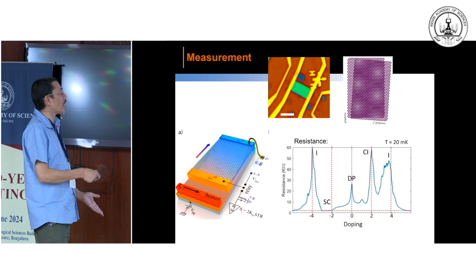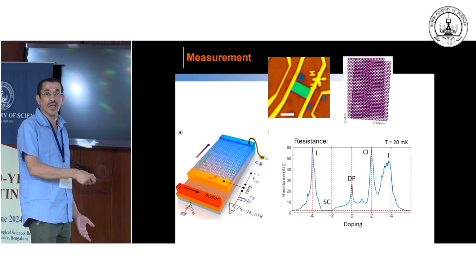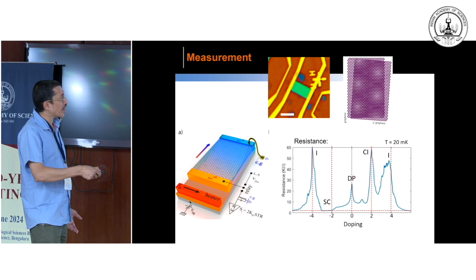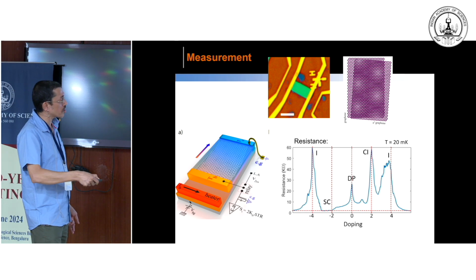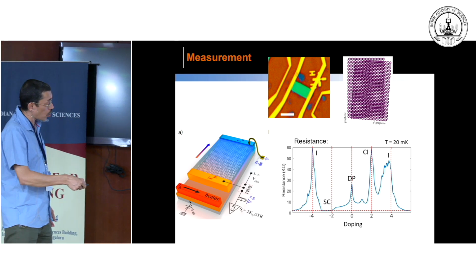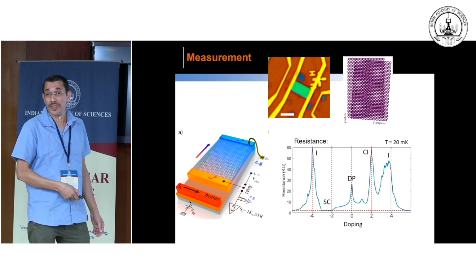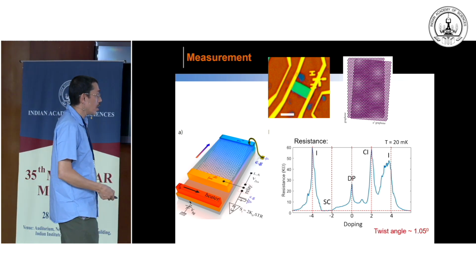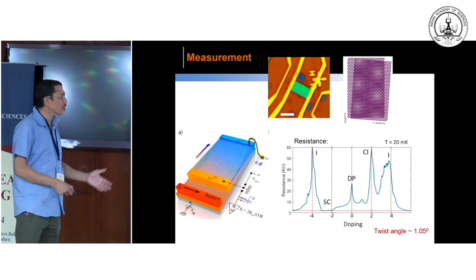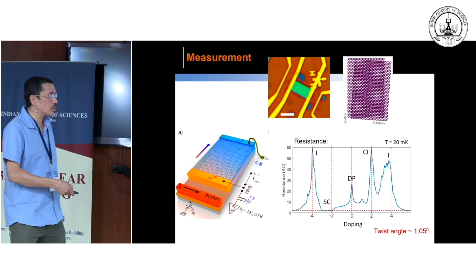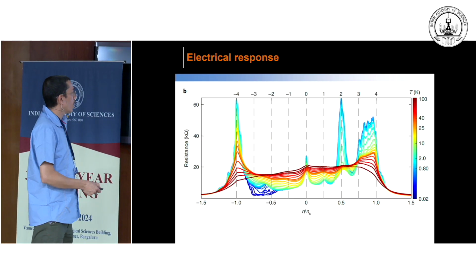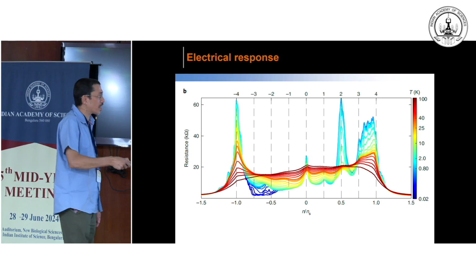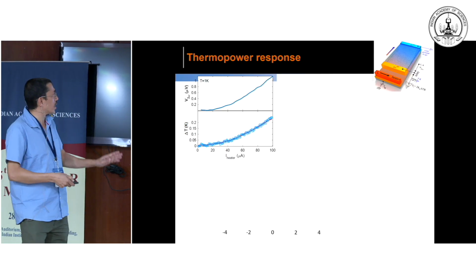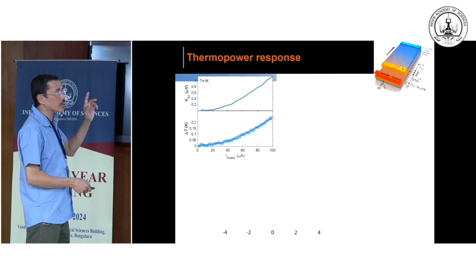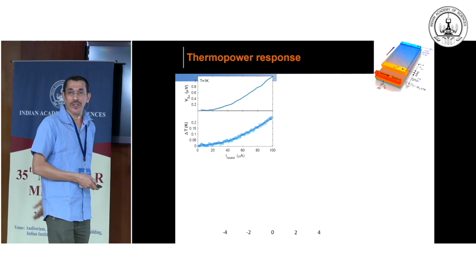So this is a unique example of what the magic angle twisted bilayer graphene resistance response as a function of carrier concentration looks like. In fact, in this device we also saw, on the hole side, that the superconductivity dome also exists in the system. This device turned out to be 1.05, and this is the resistance versus temperature. Again, it shows lots of interesting physics, but that's not part of the talk. Now let's do the thermoelectric or thermopower measurement.